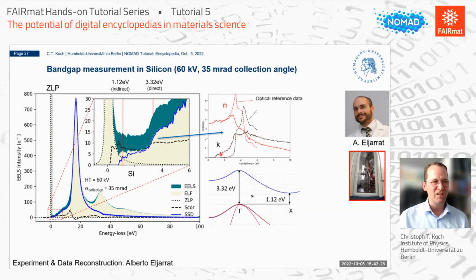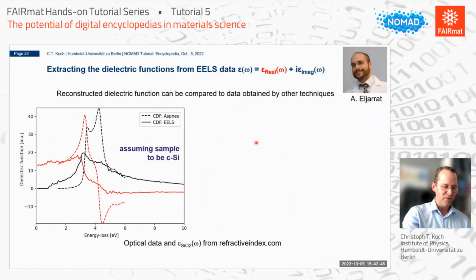And you see, they don't agree very well. The band gap kind of comes out right, the direct and the indirect band gap, but for the dielectric function itself, you would say that's sort of a good agreement, but not very good. Now this is a different representation, with the real and imaginary part of the dielectric function. You can see the disagreement is even worse than in this N and K representation.